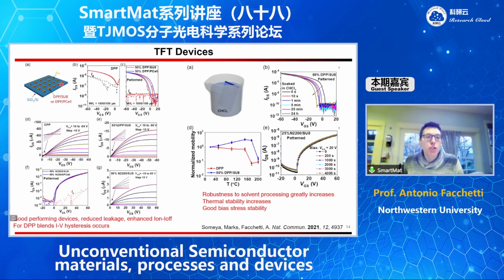In terms of charge transfer, we made the devices. I don't have time to go into detail, but this is an example of IV curve for the polymer. If it's not patterned, you have a lot of leakage current and a very poor on-off ratio. If it is patterned, the leakage is negligible because there is no parasitic current. You have a nice on-off ratio. There is a little bit of hysteresis in the case of the DPP polymer.